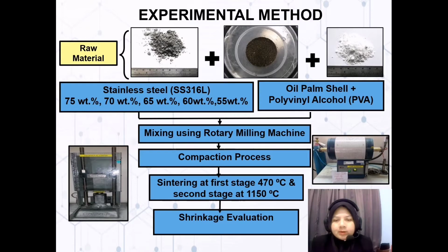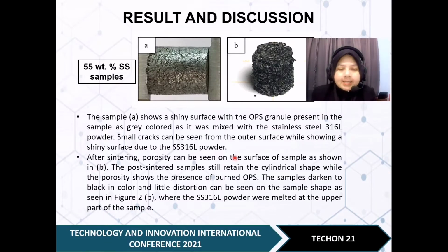Okay, this is the experimental method for my research discussion sections. As you can see here, these are the 55% stainless steel samples. Figure A is the sample before sintering and figure B is the sample after sintering. Before sintering, we can see the shiny surface on the sample. This is due to the stainless steel powder, and we can see cracks in the samples here. This is because the oil palm shell granules are different in size and shape from the stainless steel.